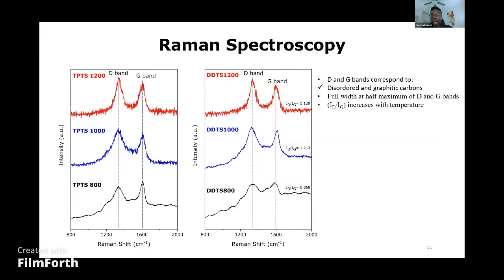Further characterization was done on the silicon oxycarbide ceramics that are derived from these polymer precursors between 800 and 1200 degrees centigrade. In all the silicon oxycarbides, we do observe the presence of D and G bands, which correspond to the presence of sp2 hybridized, disordered, and graphitic-like carbons. By integrating these peaks at their full width at half maximum, we're able to find the relative amounts of disordered to graphitic-like carbons. And what we see from our results is that with increasing pyrolysis temperature in general, we do see a significant increase in the relative amount of disordered free carbons compared to graphitic-like carbons, which is pretty interesting to see.